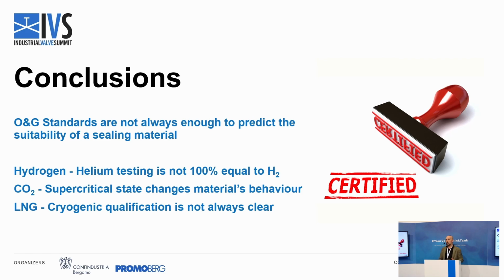For the CO2, there's no qualification process at the moment whatsoever, which is not an issue if we are talking about gaseous CO2 or liquid CO2. But if we have supercritical CO2, this lack of testing and certification could be catastrophic because of all the evidence that we already see: plasticizing of elastomers, deformation of plastics, PTFE removal from the compression packing. So it can bring a lot of problems.